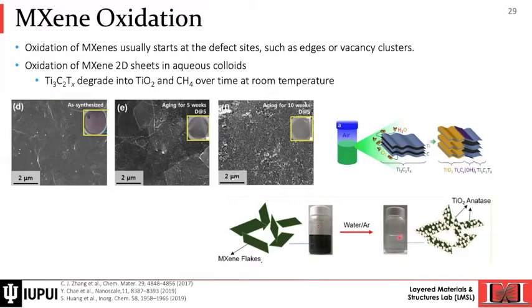And here's a schematic that I got again from Professor Mochalin's paper. It shows that MXene goes from MXene flakes to TiO2, almost all TiO2, maybe some carbon covered around it. And here's a schematic that comes from the first oxidation study that was published in 2017 that shows that MXene oxidation starts at edges. So I want to basically make it simple. MXene in water over time will go from a carbide to oxide.